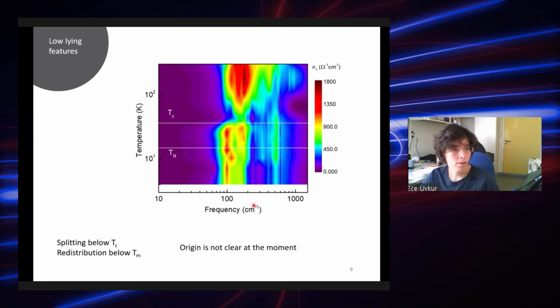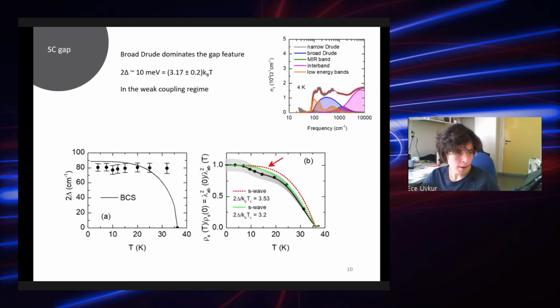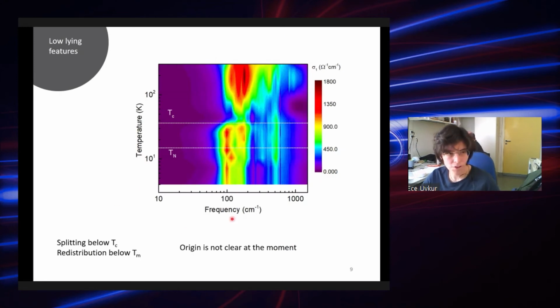And of course, when the europium orders, they also feel a bit, but this has actually never been proved, because technically when people look for the dominant bands around the Fermi energy, they of course look for the iron bands, which is indeed the dominant one. So it would be nice to know if there are some europium bands around the Fermi energy. Okay, so even though these low-lying features were weird, this clearly shows that they are not coming from the measurement setup itself. It's something intrinsic to the europium system, which is missing in the calcium case.